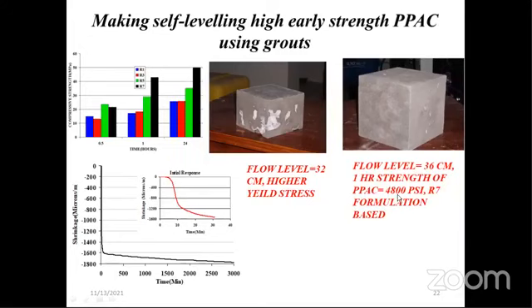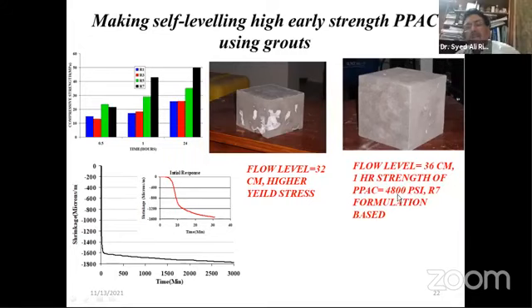and then I achieved the strength of 4,800 psi in about 1 hour, and then it gave us a complete bond with the rest of the damaged structure, and then gave us a very nice finish. So the grouts can be used, self-consolidating grout systems can be used to make these kind of repairs.